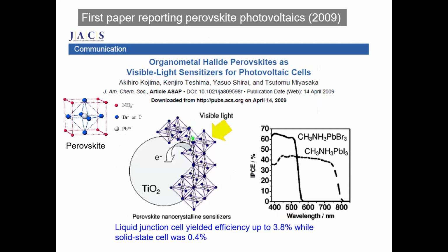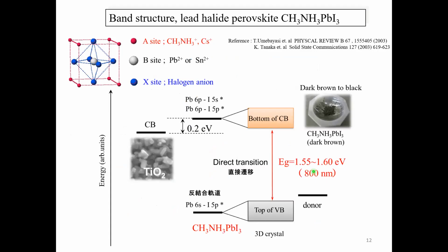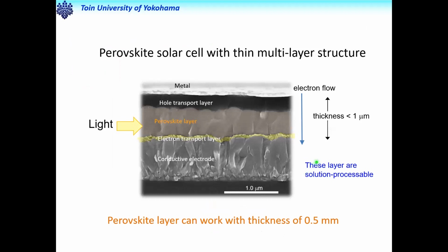We published the first result in 2009, depositing perovskite crystals on TiO2 semiconductor to sensitize TiO2, using perovskite as a visible light absorber. We found the change in the spectral sensitivity between bromide and iodide. It's the first paper. Fortunately, the perovskite crystals can sensitize TiO2 by injecting the photo-excited electron into TiO2, causing a so-called photocurrent. The band gap was typically 1.5 to 1.6 eV. This indicates all visible light is efficiently absorbed by a single layer of perovskite. So the thickness is also very, very thin.